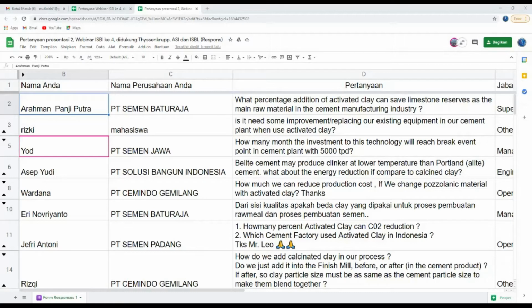So how much can we reduce the production cost if we change pozzolanic material with activated clays? This is what I also showed you in the business case here. I'm not only replacing pozzolanic material here, but I'm also replacing a bit of limestone. And especially we are also reducing the clinker, because the activity of activated clay is quite a good one. And this allows you not just to replace pozzolanic material, but also to reduce the clinker factor, which is the main lever at the end.